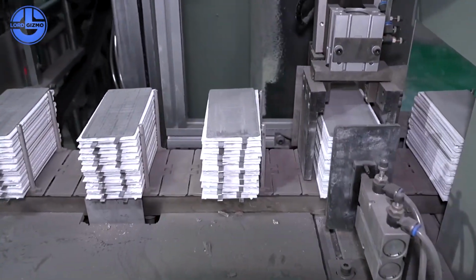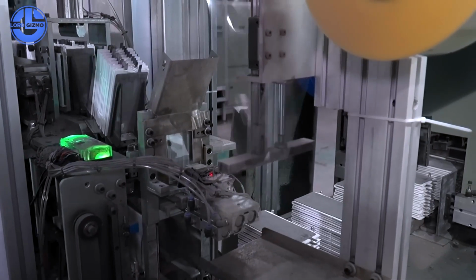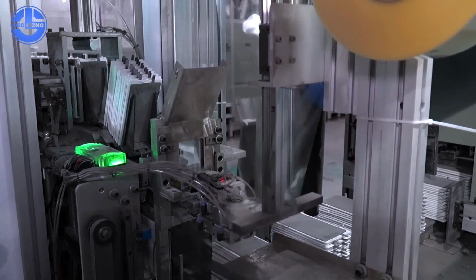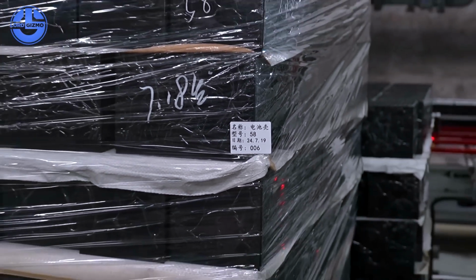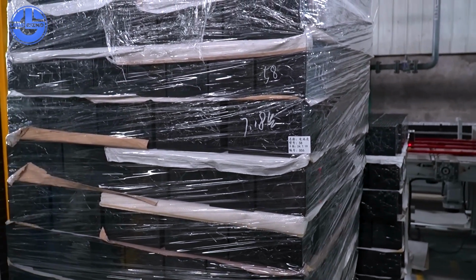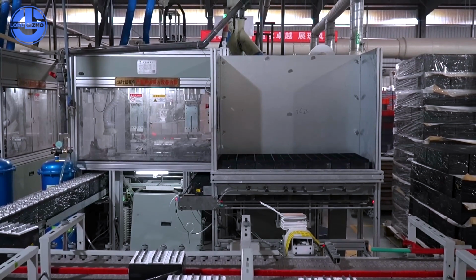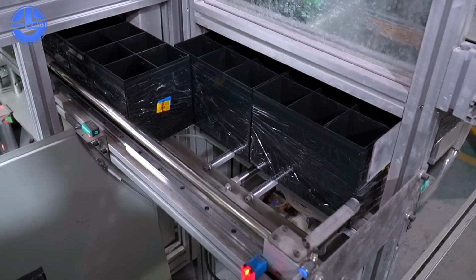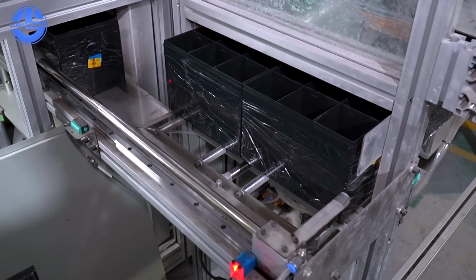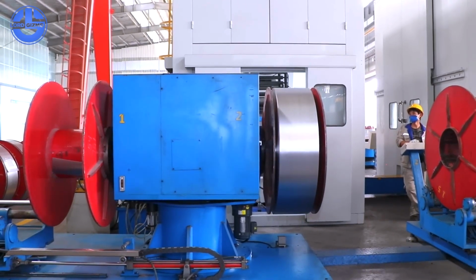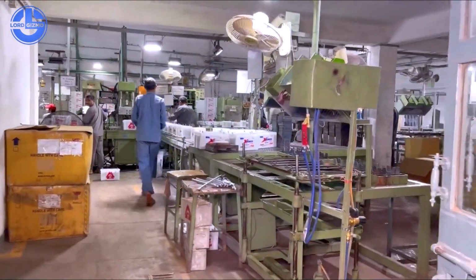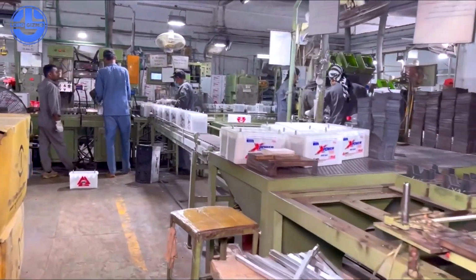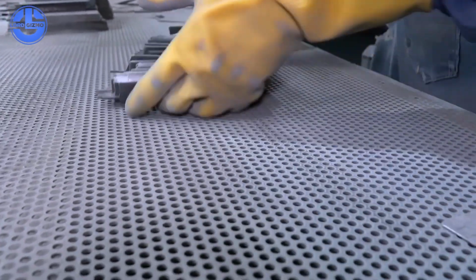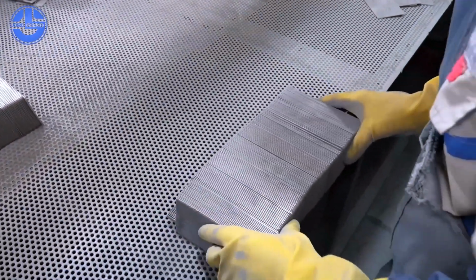Once the slurries are perfect, they begin their transformation into actual electrodes through a process that's part printing press, part precision engineering marvel. The coating process uses machines that cost tens of millions of dollars and move with accuracy measured in micrometers. Picture a printing press designed by rocket scientists. That's essentially what these coating machines are. Metal foils thinner than human hair move through these systems at speeds that would make your head spin, yet the coating thickness variation across entire sheets is less than the thickness of a soap bubble. The copper foil for anodes and aluminum foil for cathodes must be absolutely flawless. Any microscopic defect could create a weak point leading to battery failure. These foils are so thin that handling them requires special techniques. Too much tension and they tear, too little and they wrinkle.